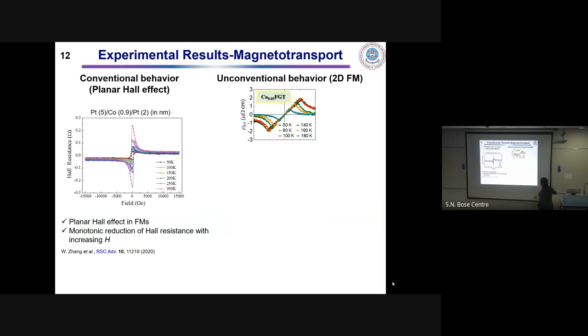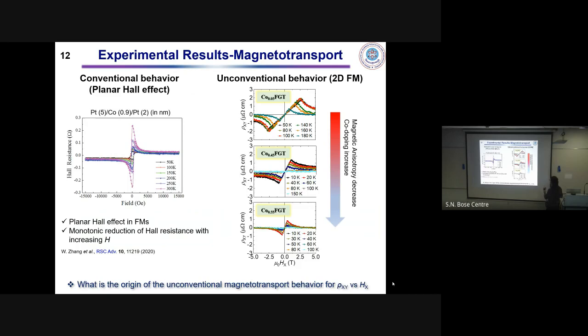It increases, it shows a cusp-like feature, and then decreases. That's why we are calling it an unconventional magnetoresistive behavior, and we studied both the concentration dependence as well as the temperature dependence of this transverse Hall resistivity as a function of magnetic field applied in the plane of the sample, or perpendicular to the c-axis.